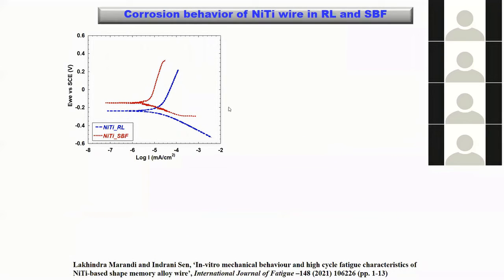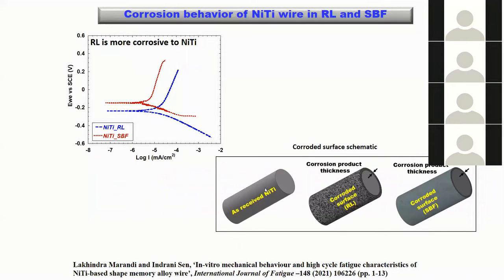Okay, now the pH levels of the Ringer's lactate and the simulated body fluid are different, and that leads to the Ringer's lactate actually being more corrosive to nickel titanium. As I said, nickel titanium is overall corrosion resistant to some extent. So what it does is it forms a protective layer of corrosion product on the surface itself. It forms chlorides and oxides and a layer on the surface. What we found is that this layer is much thicker in the case of the Ringer's lactate, which has a lower pH. In comparison, when we immerse this in SBF for a prolonged time, we still have a corrosion resistant layer forming, but this layer is quite thin in the case of SBF. Okay, so with this knowledge, we progressed to do the tensile test.